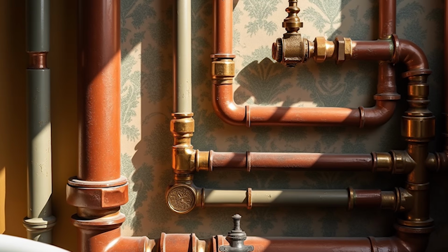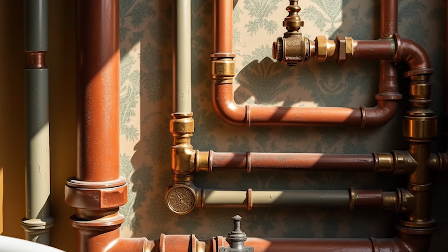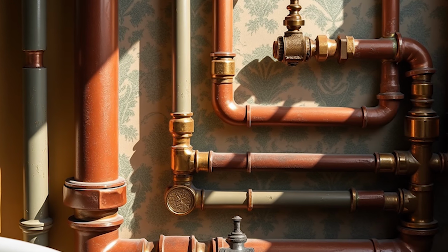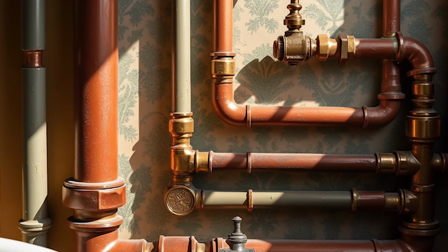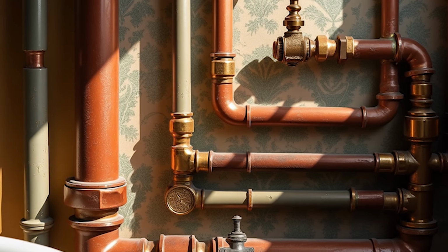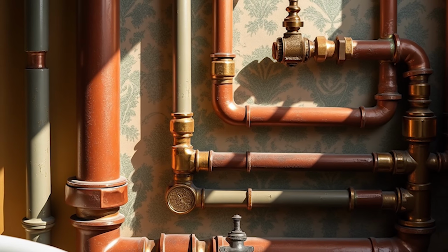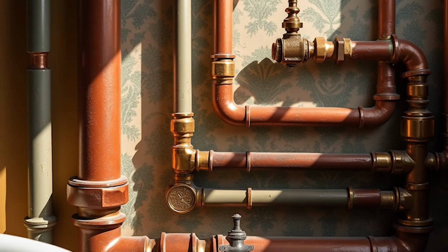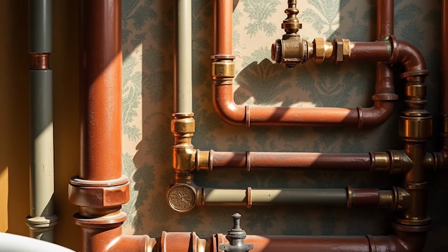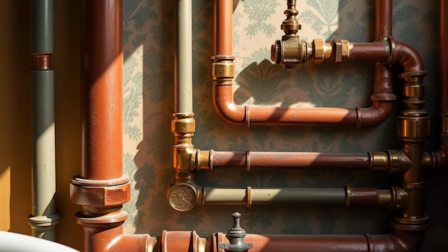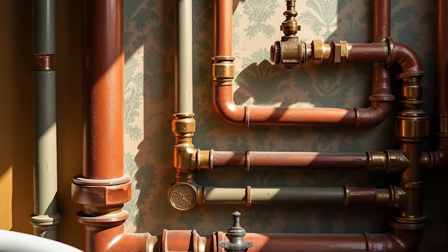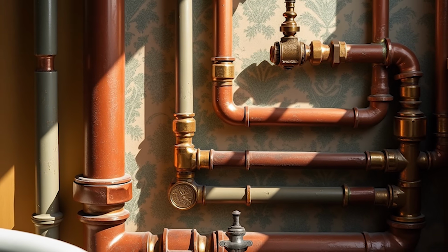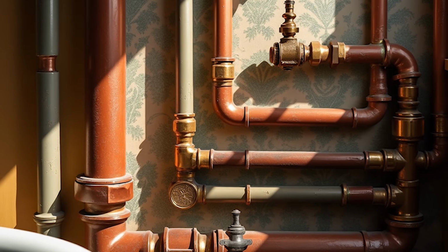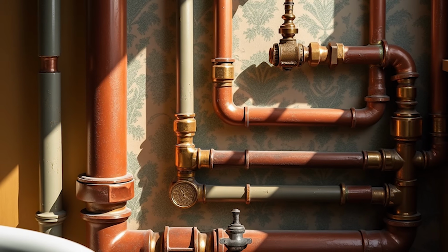C12200 copper delivered 99.9% purity with phosphorus content held between 15 and 40 thousandths of a percent. The phosphorus acted as a deoxidizer, removing trapped oxygen that created weak points in the crystal structure. Every piece that entered his mechanical rooms had been processed to eliminate the hydrogen embrittlement that plagued cheaper alternatives. But chemistry alone wouldn't win the argument.